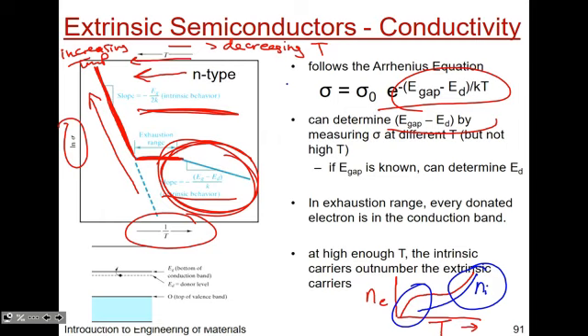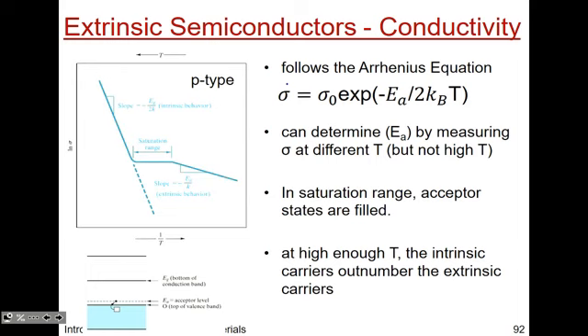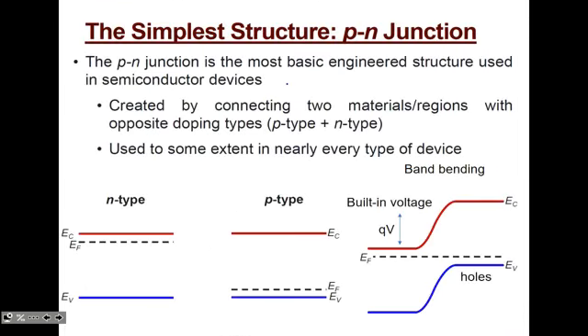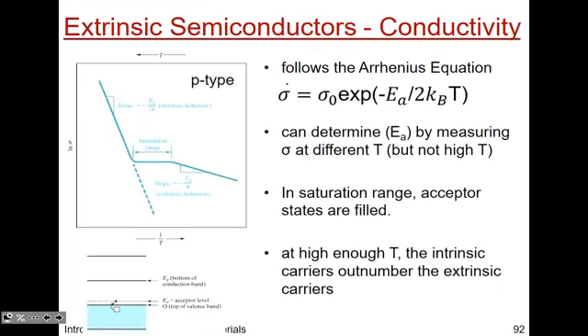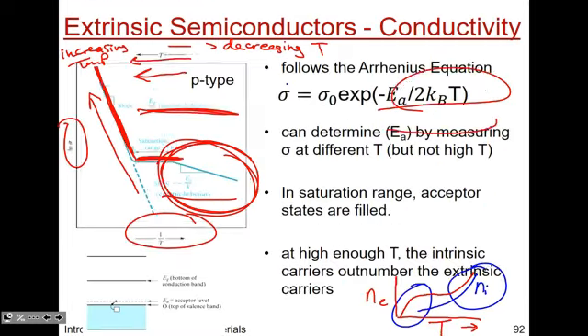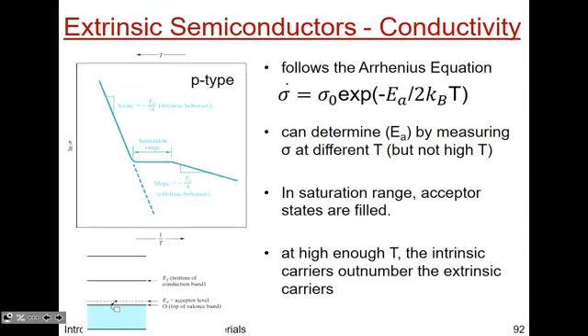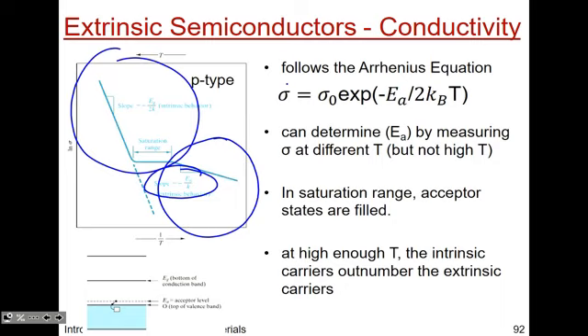It changes a little bit with P-type. So you can backtrack that out. I don't have P-type on here, but the slope changes. Actually, I think I have it here. For P-type, it's here. So for P-type, the slope is a little bit different. It's just the energy of your acceptor state divided by Boltzmann's constant, and that dominates the lower temperature regime. At high temperature regime, it's just your band gap divided by 2 times Boltzmann's constant. And that's it. So similar behavior governed by slightly different energetics, and that's about it.